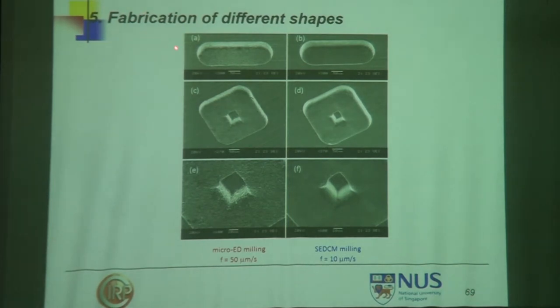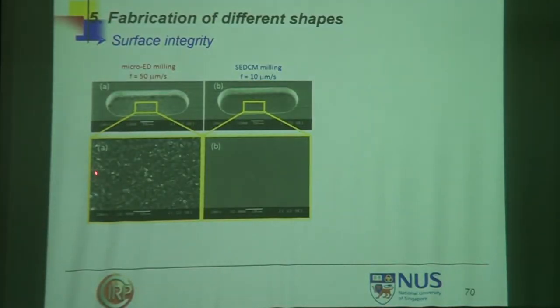Then fabrication of different shapes. These are different shapes you can do. Again, whether you do it at feed rate of 50 micron per second or 10 micron per second, that makes a lot of difference. At 50 micron per second, only EDM is taking place, and if it is 10 micron per second, EDM plus ECM is taking place. Now, to get the concrete result, at 50 micron per second, normal pulse, you get a very rough surface, and with EDM plus ECM at 10 micrometer per second, short pulse, you get a complete nano surface.